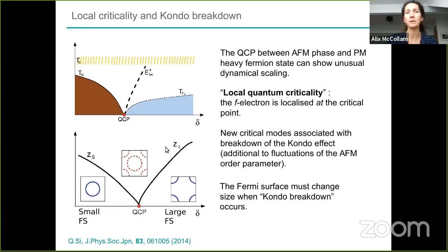The local criticality picture is somewhat different. In a number of systems, ytterbium rhodium 2 silicon 2 is one, but there are others, there's an unusual scaling observed in this particular region of the phase diagram. So this is not a straightforward phase transition from order to disorder, quantum order to quantum disorder. So we have an unusual scaling, and the idea is that the f-electron just becomes localized as you go from the heavy Fermi liquid phase into the antiferromagnetic phase. You have an abrupt localization of the f-electron right at this point, and there are new critical modes associated with this, not just the fluctuations of the order parameter, but additional modes, and this changes the dynamics of the system and gives you different physics.